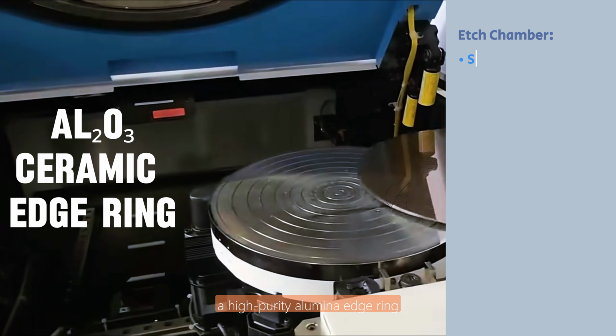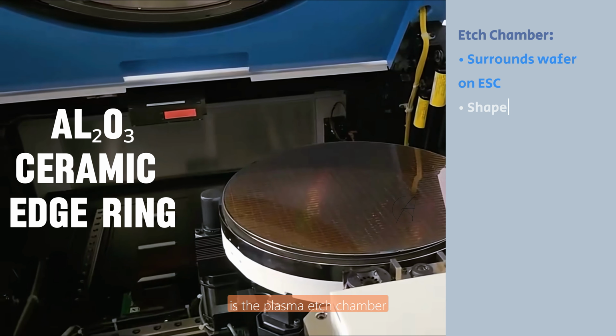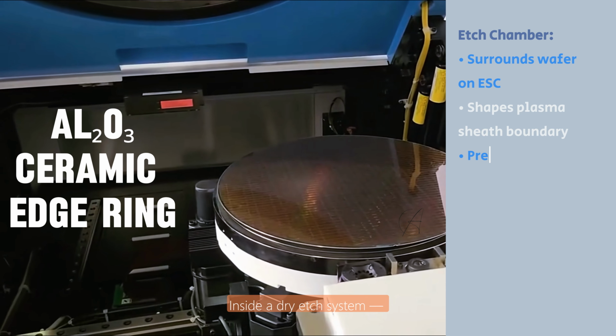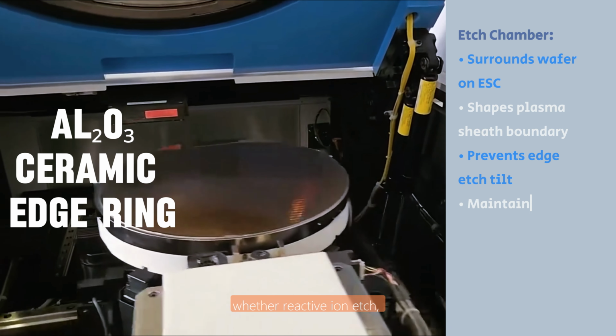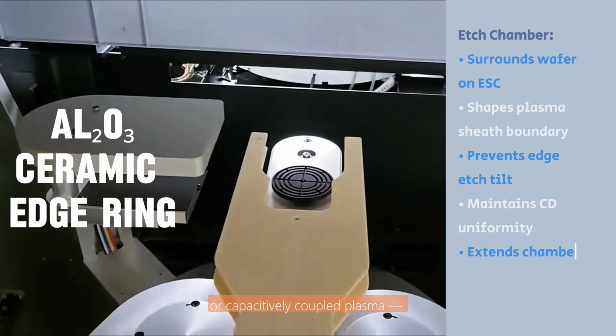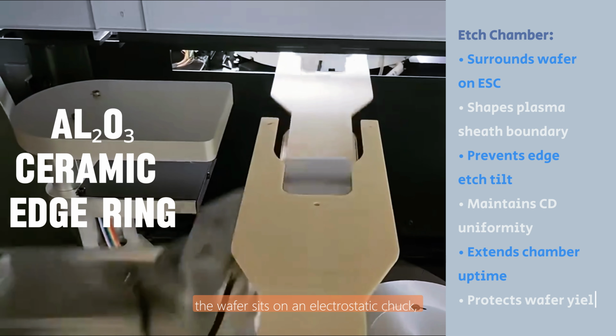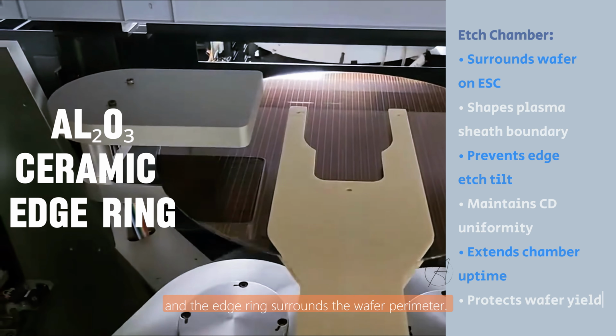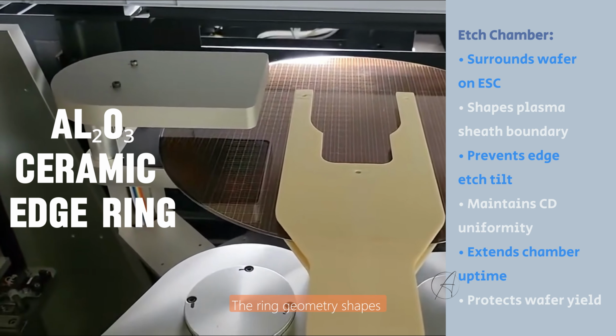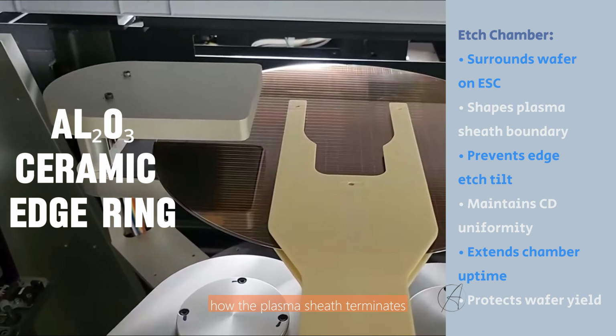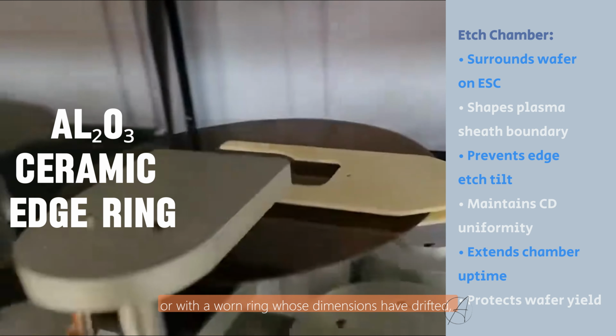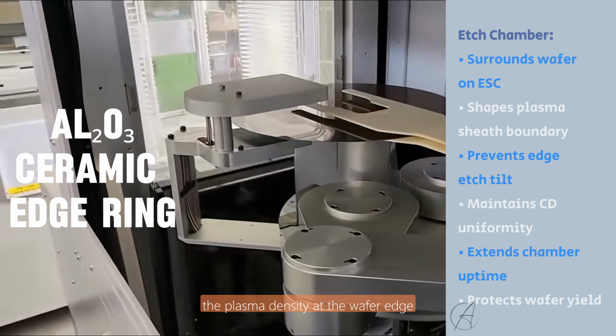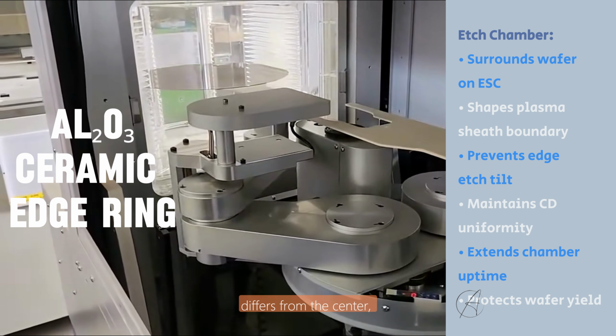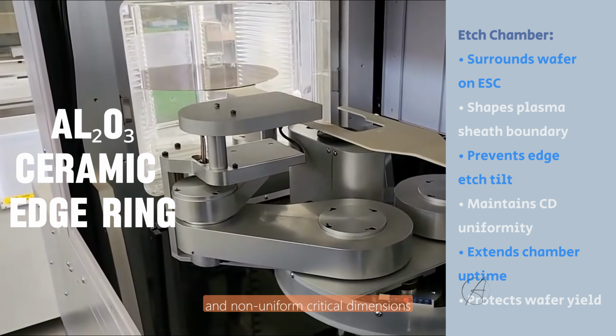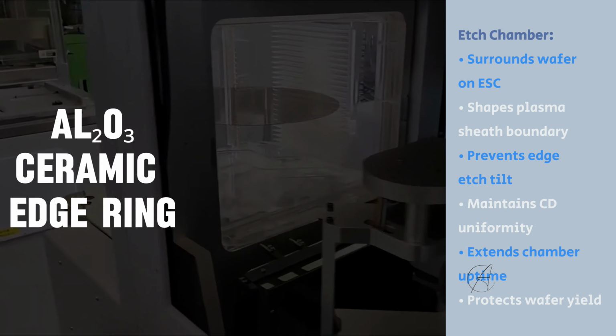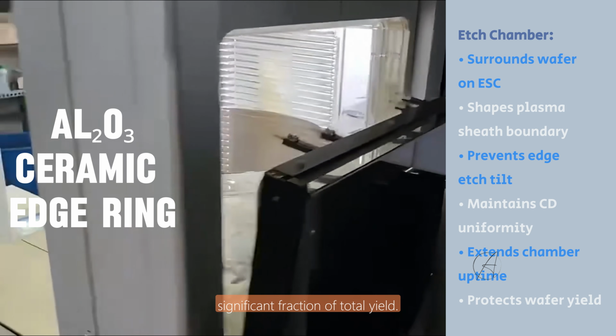The defining application for a high-purity alumina edge ring is the plasma etch chamber in semiconductor fabrication. Inside a dry etch system, whether reactive ion etch, inductively coupled plasma, or capacitively coupled plasma, the wafer sits on an electrostatic chuck, and the edge ring surrounds the wafer perimeter. The ring geometry shapes how the plasma sheath terminates at the wafer boundary. Without the ring, or with a worn ring whose dimensions have drifted, the plasma density at the wafer edge differs from the center, causing tilted etch profiles and non-uniform critical dimensions on the outermost dies, the dies that represent a significant fraction of total yield.